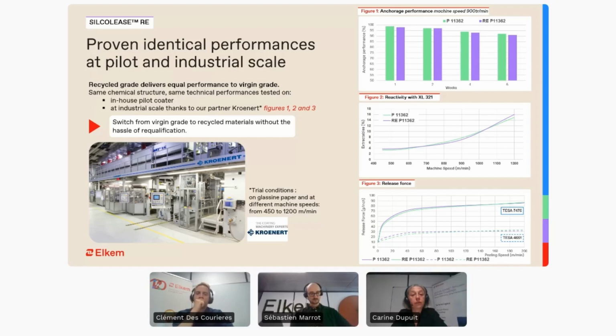We also had the opportunity to run trials at real industrial scale on an industrial coating unit located at our partner Kroenert, the well-known machinery supplier. Two versions of the SILCOLEASE P11362 have been processed, the virgin one compared to the recycled grade. Many trials have been conducted at critical conditions, like 900 meters per minute, and even at 1,200 meters per minute. All these trials have been conducted without any issue.